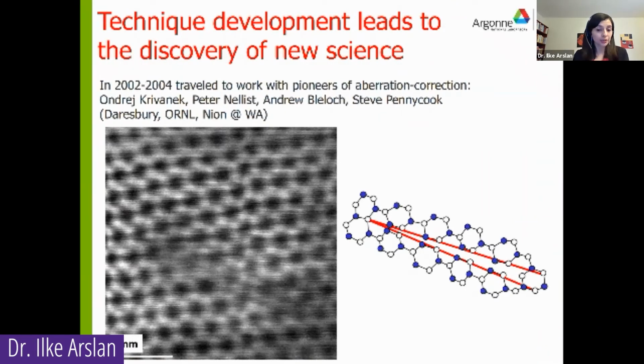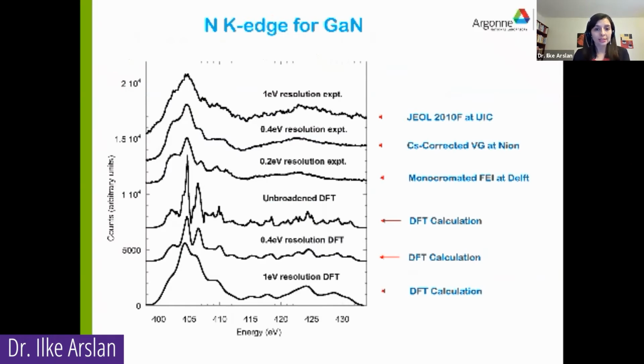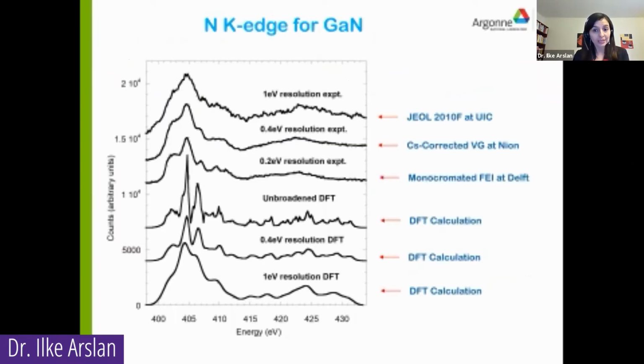And it turns out that the reason is because they were not electronically active. So I did a bunch of aberration-corrected microscopy, monochromated spectroscopy, and I even tried some DFT calculations as part of my PhD thesis, and decided I wanted to stick to being an experimentalist to figure out the fine structure and details of what was happening in gallium nitride and at dislocations.